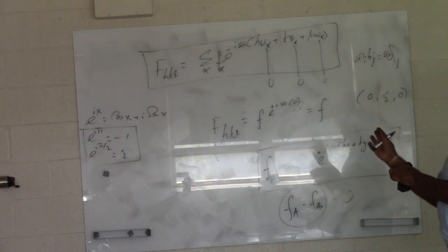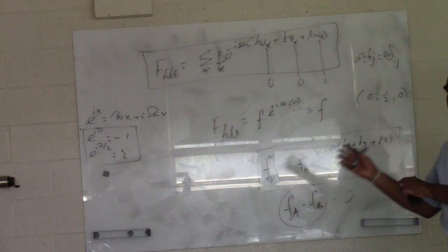Even number, right? So then they all become positive. But if you have mixed indices, maybe 2 of them even, 1 odd, 1 is even, 2 odd. In that case, you will see 2 of them become 1, minus 1, other one plus minus, right? Yeah, like that one. So then they cancel each other, you get 0. So if you have FCC, you get reflections when either all the indices are even or all the indices odd.